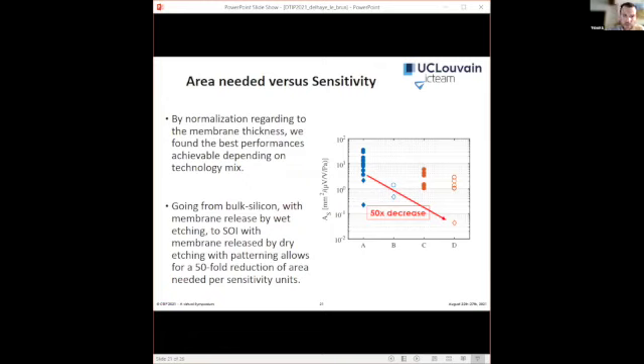And so we use these 2 experimental lines to predict the best performances that are reachable depending on the technology mix. And we can see that going from bulk silicon with membrane released by wet etching to silicon on insulator substrate with membrane released by dry etching and membrane patterning allows for a 50-fold reduction of the area needed per sensitivity units. So this is a huge improvement.